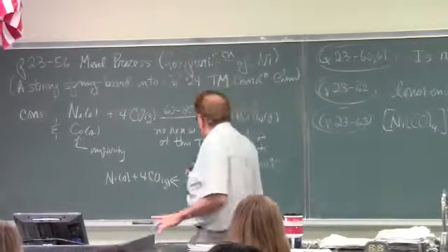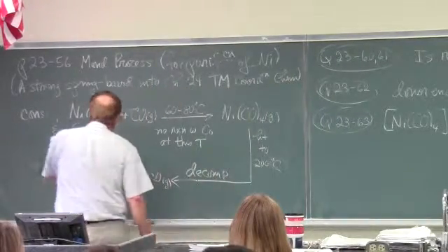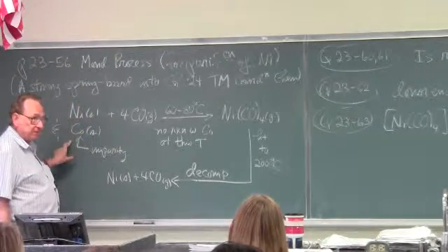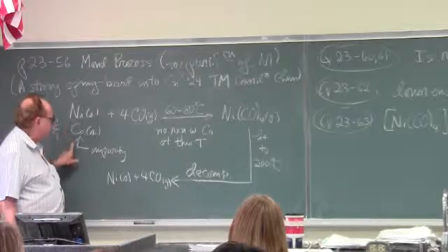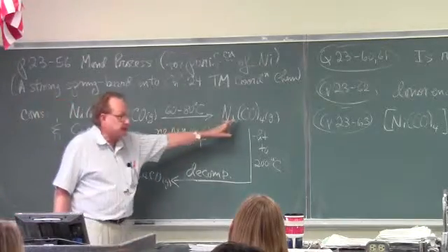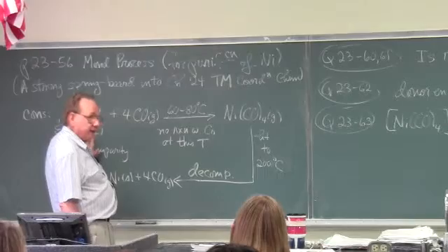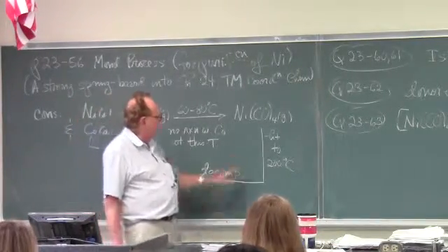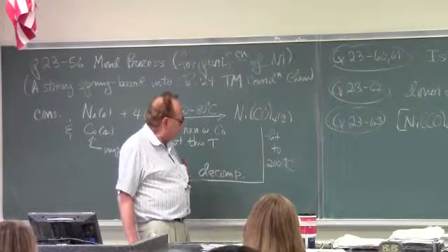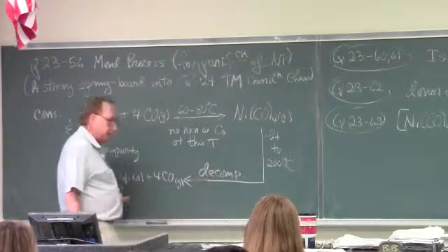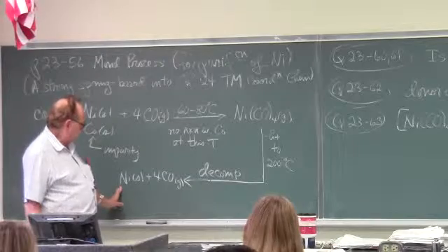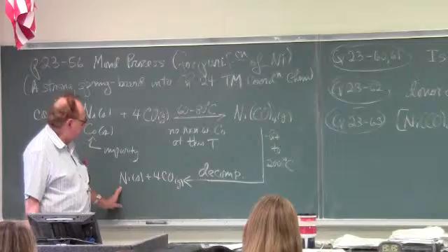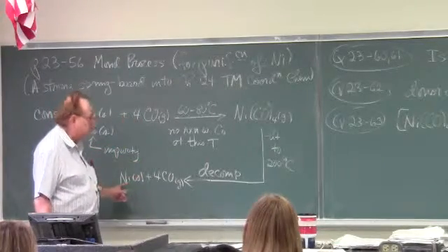Back to the chemistry. So what this reaction achieves is separation of the nickel from the cobalt. The nickel reacts, the cobalt doesn't react, the nickel compound is gas phase, and cobalt is solid, doesn't react. So the separation has been achieved. Then when we take this gas phase compound, heat it up to about 200 degrees, it decomposes, and we get pure nickel. So this shows us how, from the chemistry of metallurgy applied to nickel, we get pure nickel.